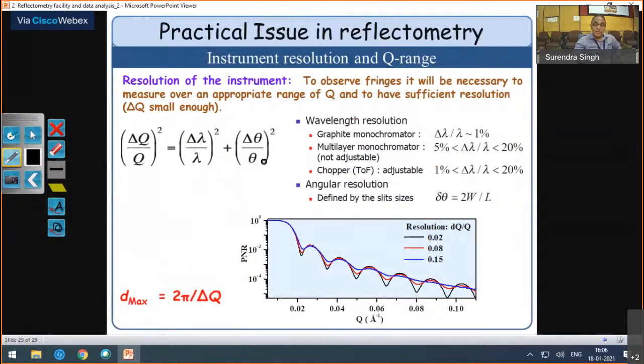So what is the effect of resolution on the reflectivity pattern? Here I have shown three resolution values and plotted the reflectivity pattern. With very good resolution, delta q by q equal to 0.02, you can see this black plot showing nice Kiessig oscillations.